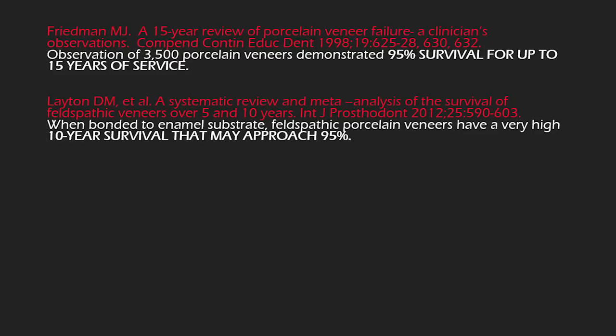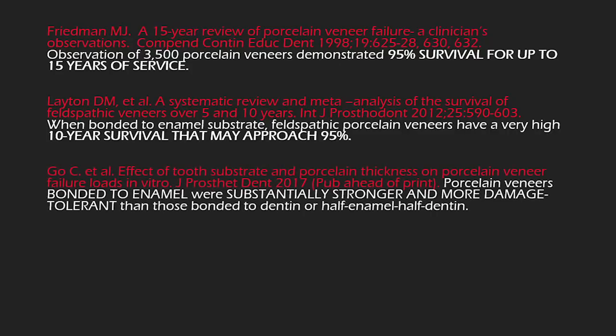There are some other studies that show a great up to 95% retention rate at 10 years, which is a great survival rate. The interesting thing about the study is when you start to look at porcelain veneers that are bonded to lesser amounts of dentin, in other words, let's say 50% enamel, 50% dentin, then the failure rate goes up, the survival goes down. So people were thinking, well, if I have a little rim of enamel around the outside of the tooth, that's all I need? Nope, in enamel we trust.